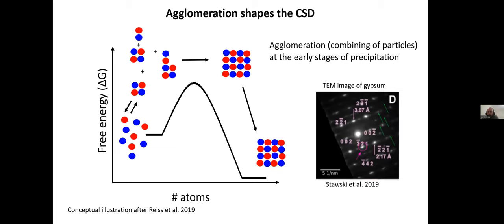While this paper was in review, there was another paper published, actually in the same journal, that studied the internal structure of gypsum. And they found out that gypsum crystals often are mesocrystals. Now, mesocrystals are crystals that diffract light as a single crystal. They have defined crystal faces, but they're built of internal defined different domains. And their conclusion was also that when the crystal was formed, it was through agglomeration of nanoparticles. So basically, we have here two observations that were published around the same time. One looked at the microsystem induced outward. The second looked at the macrosystem deduced inward, and we both reached the same conclusion that agglomeration is a major part of gypsum precipitation or nucleation. So we have new insights into the mechanisms of the crystal formation.